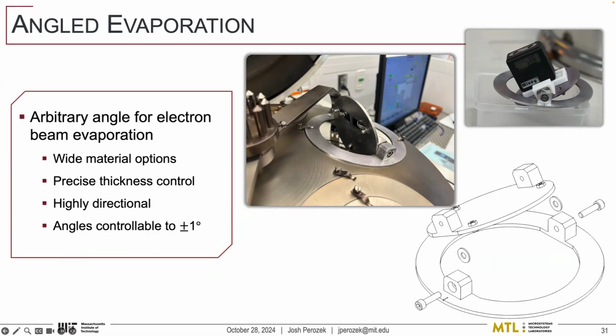You can set the angle with a digital angle finder to within plus or minus 1 degree, which ends up being more than sufficient accuracy for even the sub-micron features that we're trying to make. And it lets us use all of the fast pumping, high quality, diverse material systems that we have in the lab. So this was a key enabler to letting us really try this and iterate quickly as we go through these. So now I'll talk about how we actually fabricate the world's first self-aligned vertical GaN FinFET.